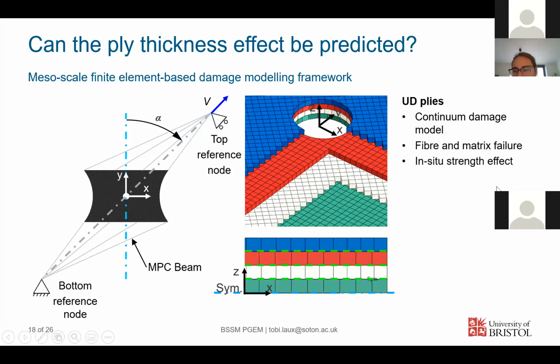Also something to mention is we consider in situ strength effects. So I'm not going to go into details, but that's something to look up if you want to predict the strength of multidirectional laminates. And then the last thing is, in between the plies, we have interfaces, and we use Abaqus built-in mixed mode cohesive surfaces in between. So what they can do, they can model discrete cracks, delamination forming in between the plies. Also, I'm not going to go into details how this works.